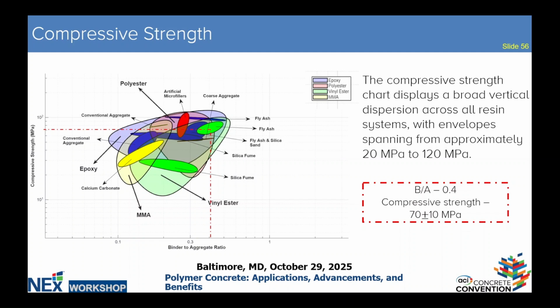So you match your binder to aggregate ratio, which is 0.4, and you just look on your y-axis through mapping, and you get a range of 70 plus or minus 10 megapascal. So with this, you know what you're working for, and it makes it easy to design. So this data was scattered data, and now it looks highly visualized and makes it easy to see what you're working out for. So this is for compressive strength.